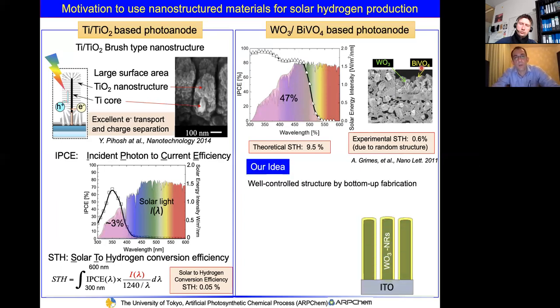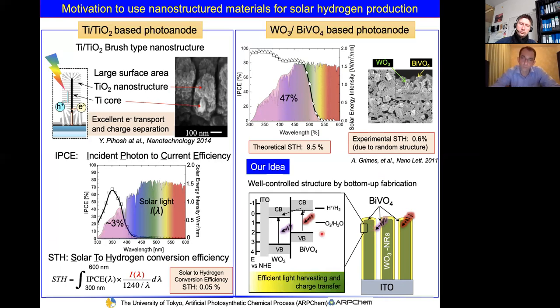However, my idea was different. How about a well-controlled structure made by bottom-up fabrication, and then covering this one-dimensional material with bismuth vanadate? If we look at the band diagram of both materials, you can see that the conduction band of bismuth vanadate is located a little higher than the conduction band of tungsten oxide. That means the generated electrons can pass through easily and reach the conductive substrate. So for such a photoactive material, we expected efficient light harvesting and charge transfer.